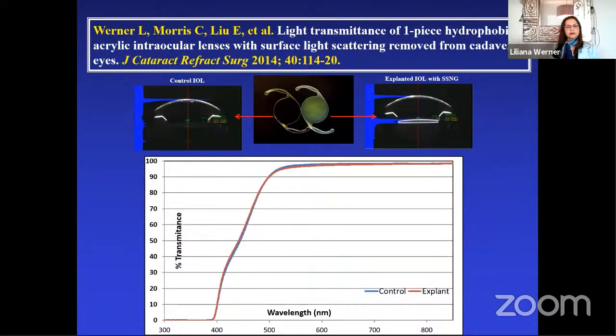The presence of subsurface nanoglistenings leads to an aspect of whitish discoloration of the hydrophobic acrylic lens when evaluated under a slit lamp at some specific angles. The nanoglistenings cause an increase of light scattering at the lens surface, which can be evaluated with the Scheimpflug technique, as you can see on the top photographs.